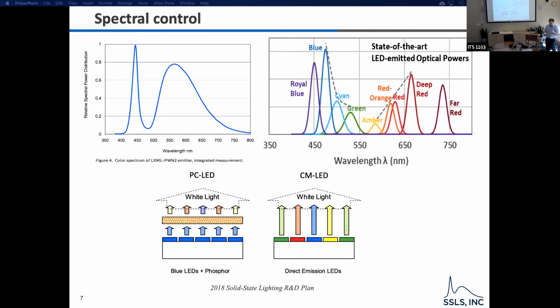And then of those photons that are generated, 90% plus get out of the semiconductor material. That's called light extraction efficiency. And when you're delivering the electrons in, 95% of the electrons make it into the semiconductor. So you're dealing with better than 90% for all these sub-efficiencies. That ultimately gives you, depending on operating conditions, very high 80, 75% efficiency. And then you have the phosphor conversion process, which is also 90+%. And you have some LED package effects, which are 90% also.